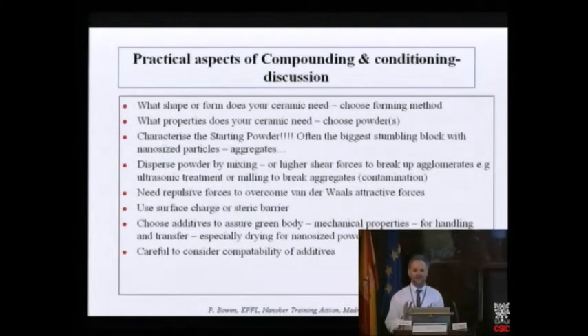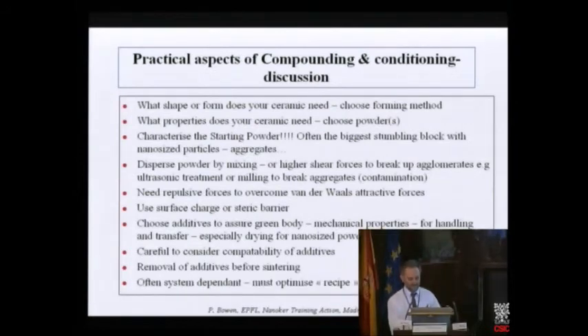You have to be careful to consider compatibility of additives. Polyvinyl alcohol and polyacrylic acid, at a certain ratio of composition, are not compatible, they segregate. So then you create the segregation of your polymeric additives, which is quite problematic. Citric acid and polyvinyl alcohol are not compatible. So there are lots of examples of incompatibility. You have to be careful when you choose the additives that they are compatible. You have to remove them before sintering.